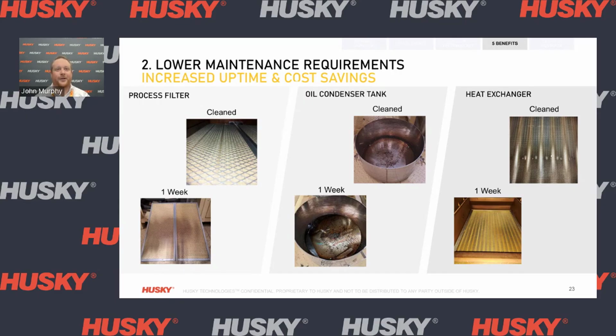On the left-hand side, you can see a typical process filter and what that can look like after 1 week of production run. We also see, for example, the oil condenser tank in the middle of the screen. After 1 week, the amount of oil it can collect and the maintenance required to clean that. And then we also see on the right-hand side, a typical heat exchanger cleaned versus after 1 week of running a challenging rPET material.